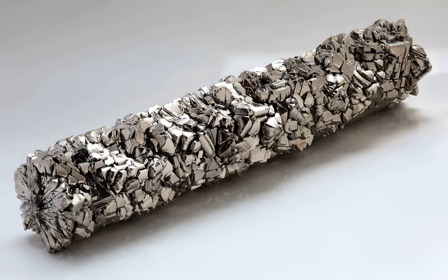When used in the production or handling of chlorine, titanium should not be exposed to dry chlorine gas because it may result in a titanium-chlorine fire. Even wet chlorine presents a fire hazard when extreme weather conditions cause unexpected drying. Titanium can catch fire when a fresh, non-oxidized surface comes in contact with liquid oxygen.